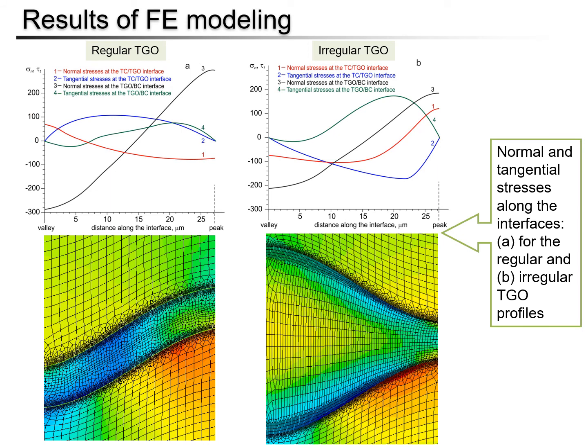And now I'd like to move on to the results of finite element method calculation for regular and irregular TGO profile. You can see in this slide, without considering interfacial debonding firstly, the distribution of residual stresses as a result of FEM modeling. For the regular TGO, the potential crack initiation sites are located at the peak of the thermally grown oxide BC interface and at the valley and the middle of the top coat and thermally grown oxide interface,